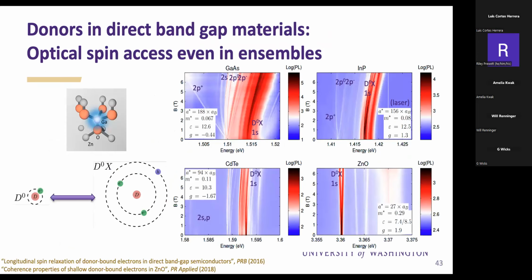And this just shows an overview that, of course, these will exist in any semiconductor. Gallium arsenide, indium phosphide, cadmium telluride, and zinc oxide are shown here. They all have different Bohr radii that are given by the material properties. They also have different g factors, which can be a proxy for spin-orbit coupling and how good the coherence might be. And what you also can see, a little less clear because it's in color plots, is very well-defined transitions of the donor-bound exciton, which enables you to have optical spin control in this case.